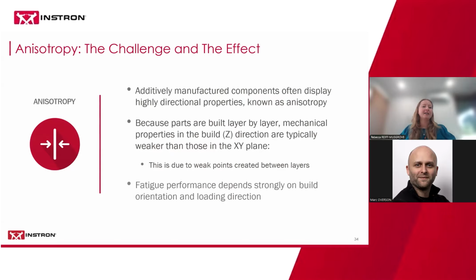Then moving on to anisotropy. Here I've combined the challenge and the effect. They're essentially the same thing. Basically, additively manufactured components often display highly directional properties, and this is what's known as anisotropy. There's a difference in properties in direction. And this is because parts are built layer by layer. So you have mechanical properties in the XY plane that are typically different to those in the build direction.